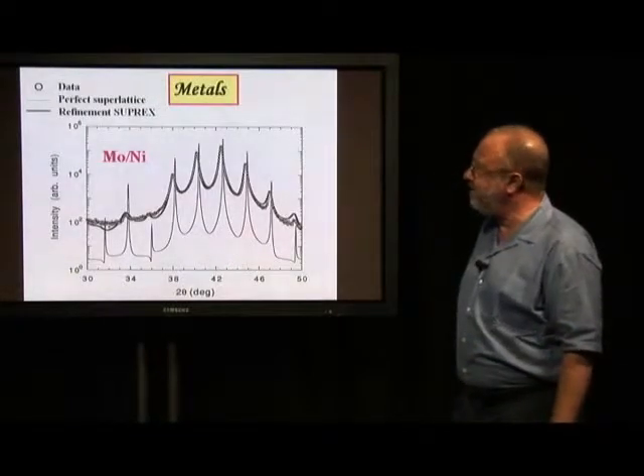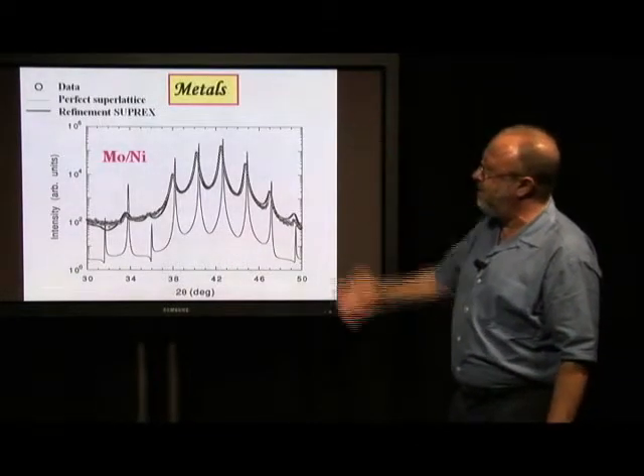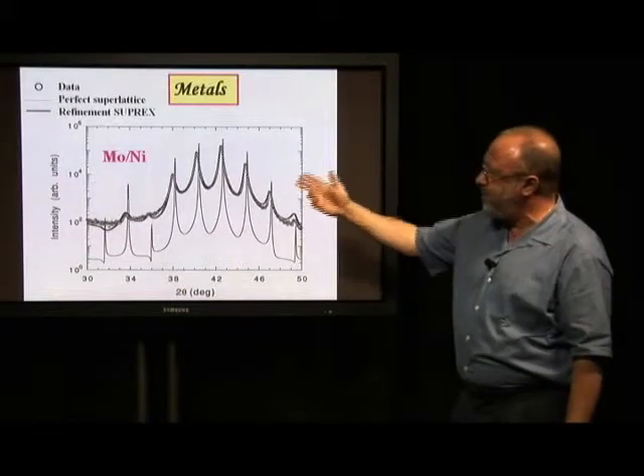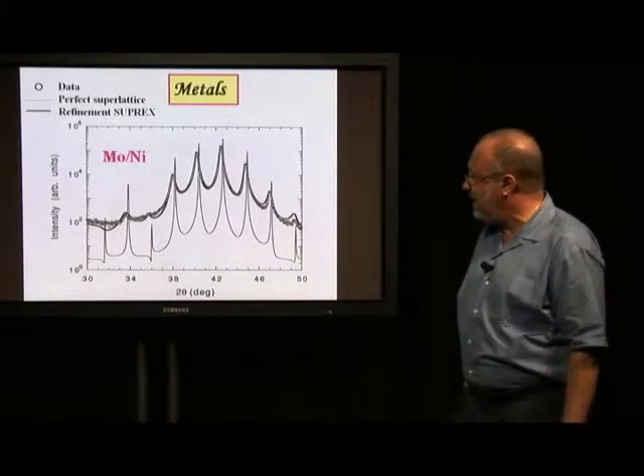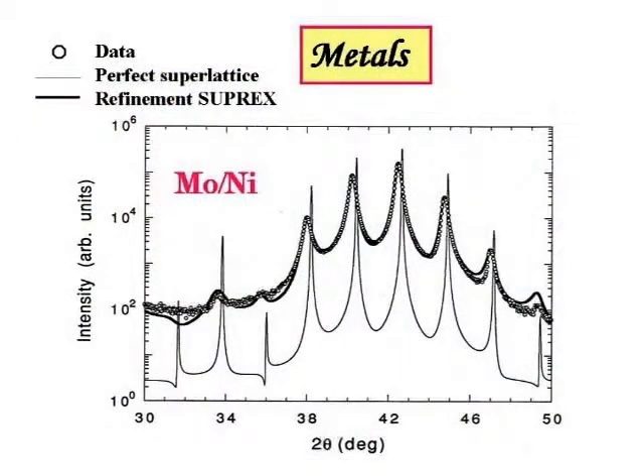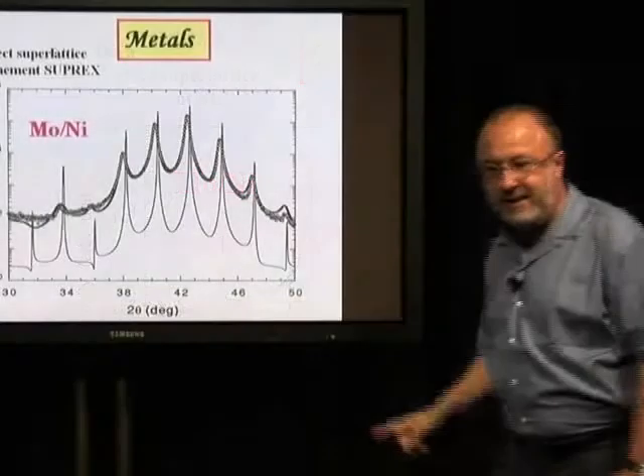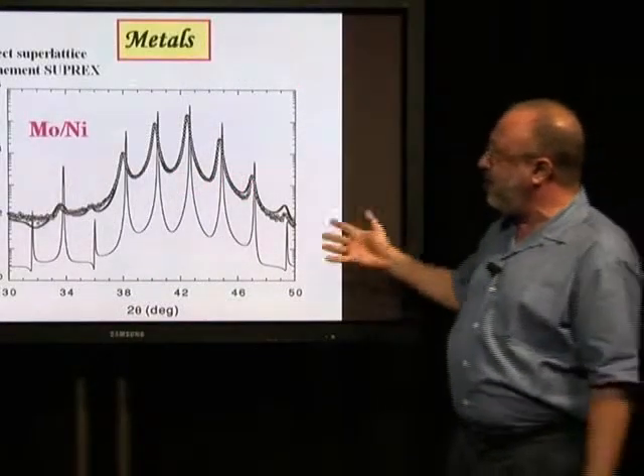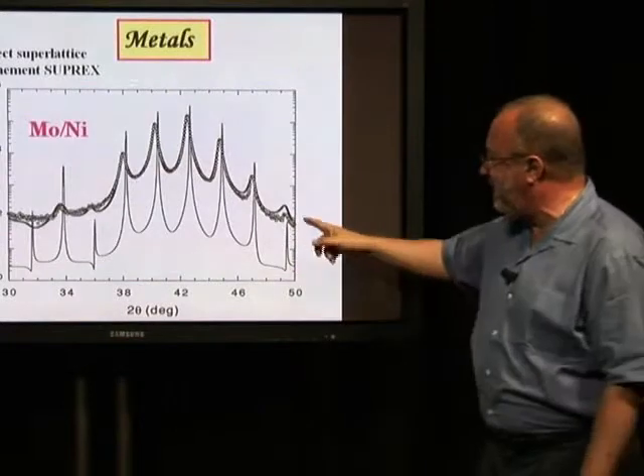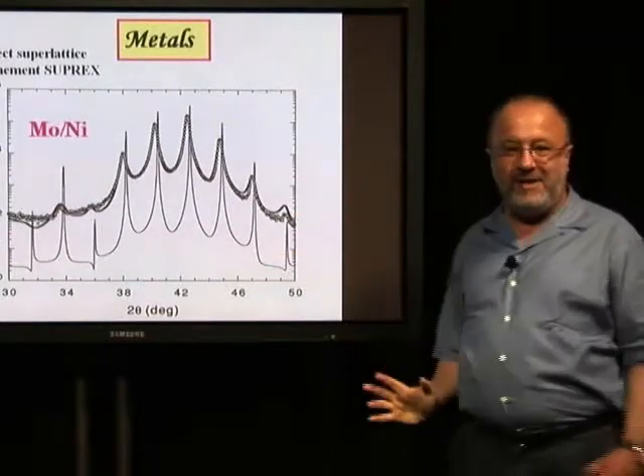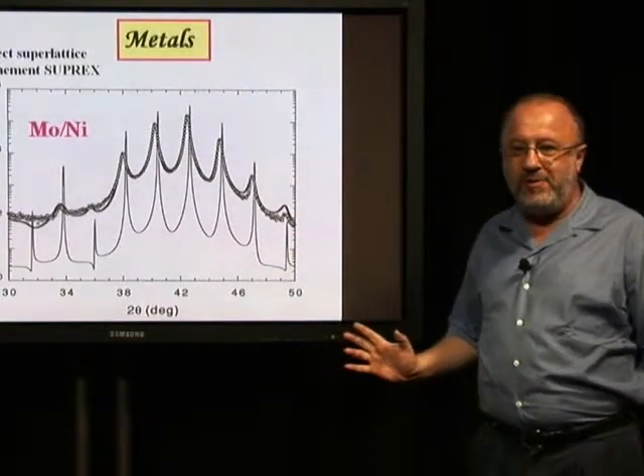And here is some example of that. Here it is a metal. This is the example of molybdenum nickel metallic superlattices. The circles here are the data. The thin line is what a perfect material would look like. And there it is, the perfect material. So this is, again, intensity as a function of 2 theta, X-ray diffraction. And you don't have to be Einstein for this. Basically, you can tell that the data does not agree with the calculation for a perfect material.